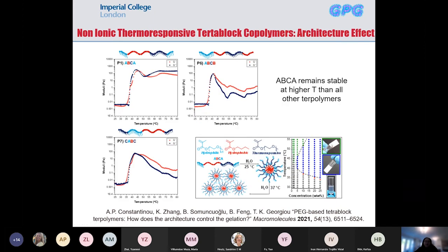These are the rheological curves that support that, and you can see in this one that you have some initial destabilization, but then it's still stable and forms gels at all temperatures. This destabilization we didn't observe visually, it was only rheologically that we observed that, but interestingly this polymer does stay stable at higher temperatures.